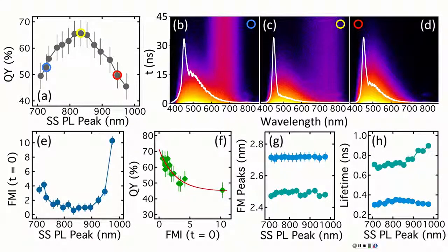My initial intuition was that... But the intensity is changing, right? You're saying the bigger the dot, the slightly higher the intensity for this blue shifted peak. No, it's big on either end, and it's low in the middle where the quantum yield is the highest. So it anti-correlates with quantum yield. That's why surface states seem to make sense, except that they should be in the gap, right?